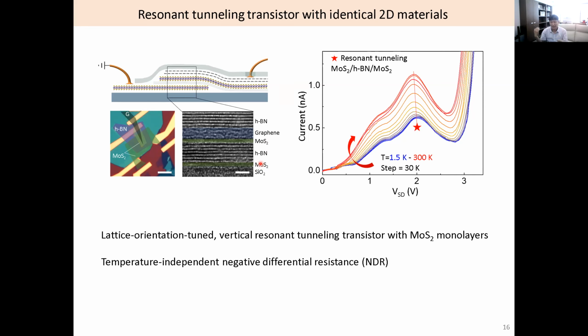This is the difference compared to other conventional tunneling devices, because as I said, we have to consider momentum for designing some devices. What happens is that, of course, I like this room temperature behavior, but physicists like this low temperature behavior. This is an IV curve of this tunneling device. This is a very simple two-terminal device. As we increase the voltage, we have current increase, and suddenly we have this decrease in current. This is called negative differential resistance. Of course, if we average out, it is positive, but here locally we have this negative differential resistance. Normally this appears when we have some resonant behavior.